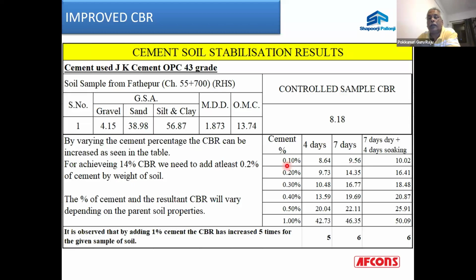So similarly, when you increase from 0.1 to say 0.5 or 0.3 or even 0.2, now when you are using it for subgrade, your subgrade material needs a maximum CBR of only 15%, because beyond that, whatever CBR you achieve, it is only adding cost, it is not adding any value, because it is not going to change any other parameters of your design if you are doing the design on a 3-layered structure using IITPAVE. So if my cement dose is 0.2%, then the CBR which we get is 16% at the end of the 11th day.